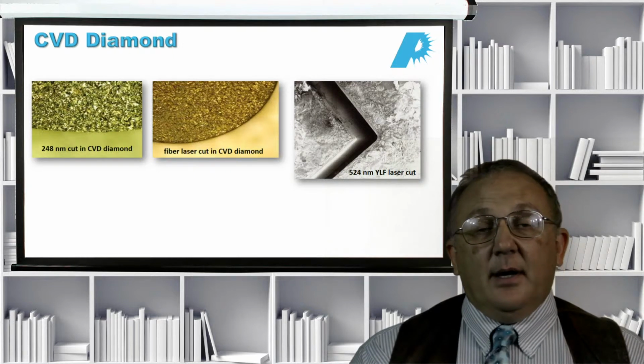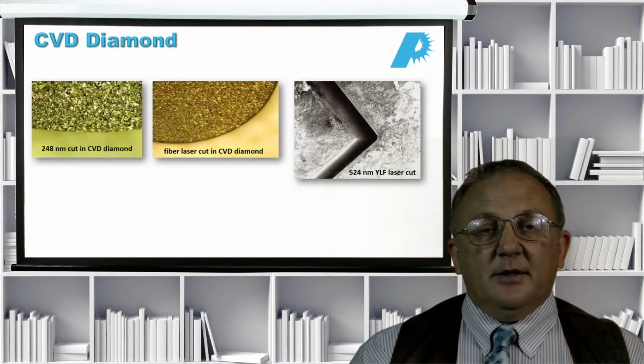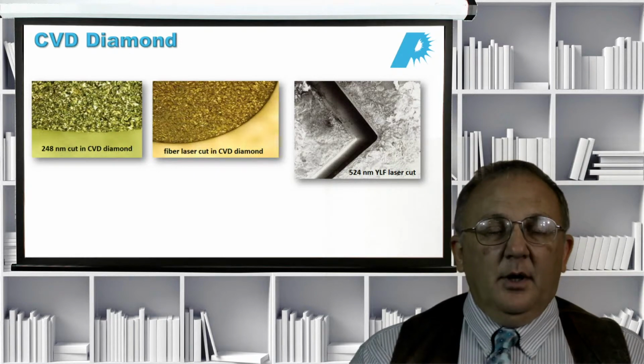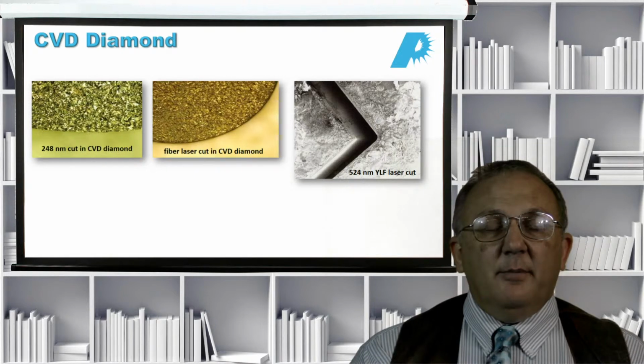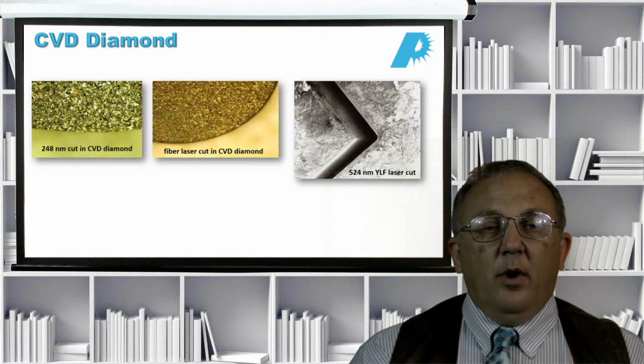And it turns out that we can cut diamond, because it's carbon, with almost any laser. Unfortunately, if you use a CO2 laser or a long wavelength laser, you're going to get a lot of charring and carbonization. The diamond reverts back to its carbon form. So that's not really an option, but if you start at 1 micron, you can make very good cuts with a 1 micron infrared laser, as you can see in the screen in the middle.